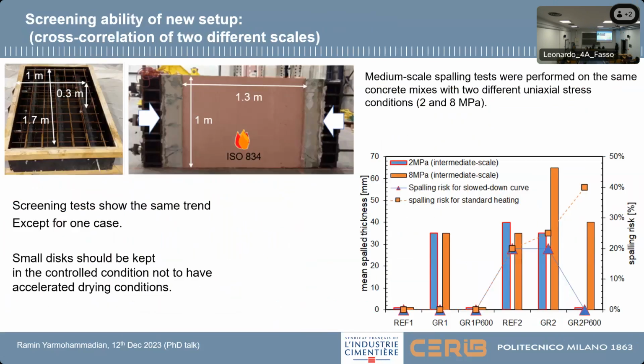So what we did until now, we tested all those samples on a small scale, but is it actually related to the real behavior of that concrete? So we tested the same concrete on a larger scale. So a large slab, 1 meter by 1.3 meter, with different kinds of initial stress, uniaxial stress, and both our test setup and the larger scale test setup give almost the same spalling risk.